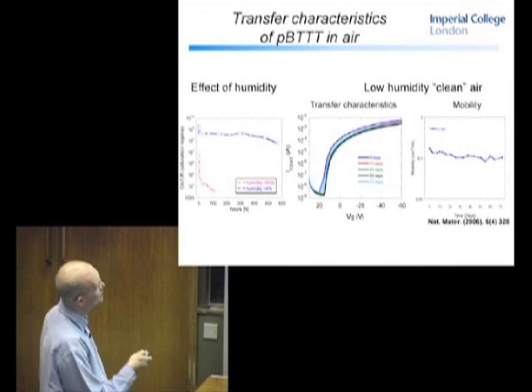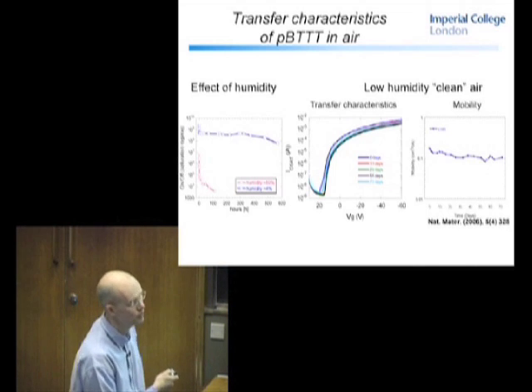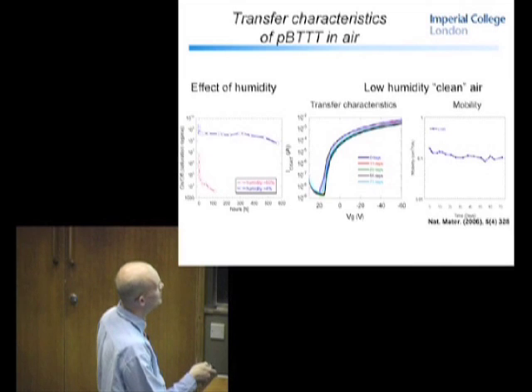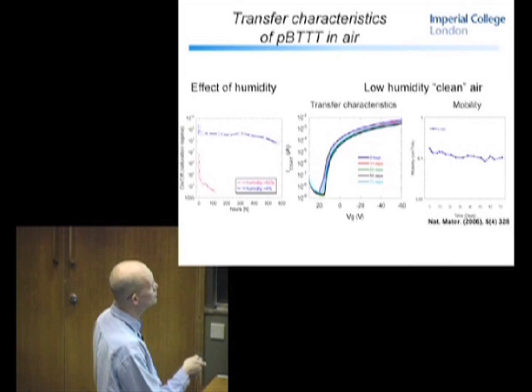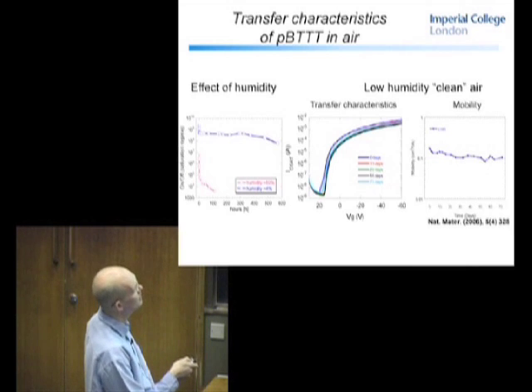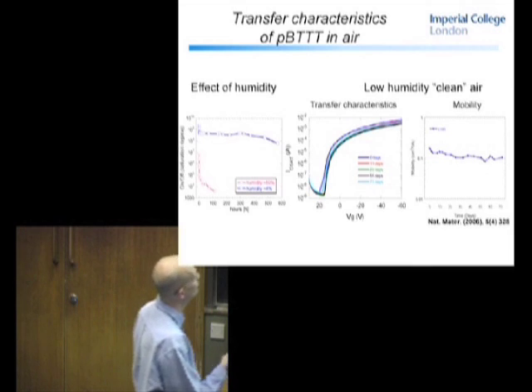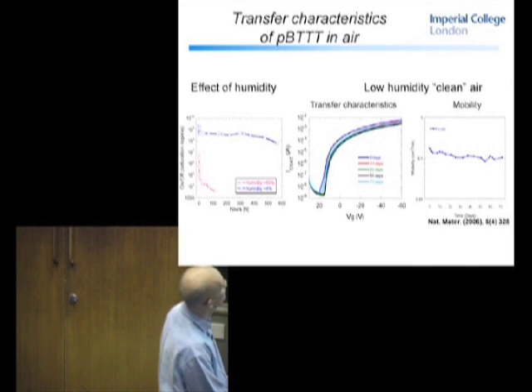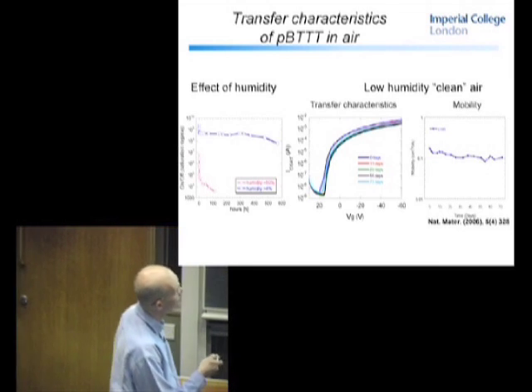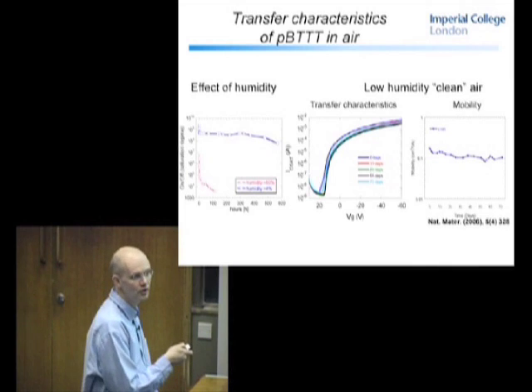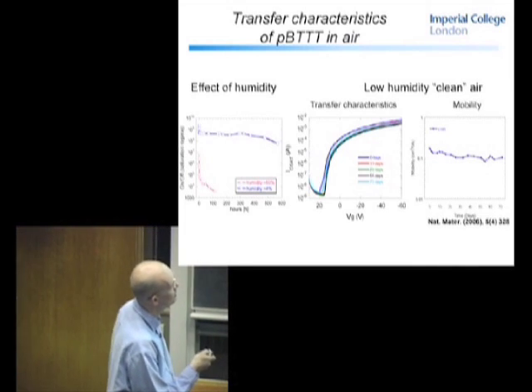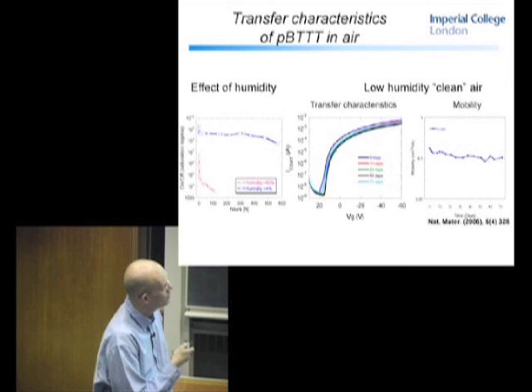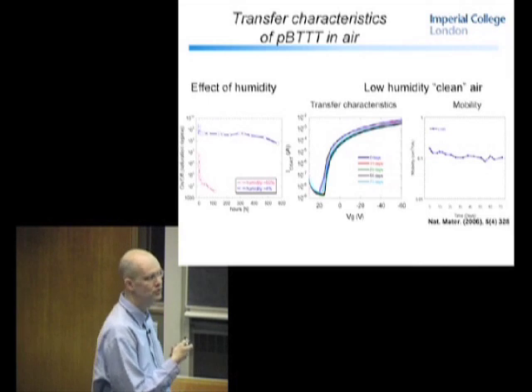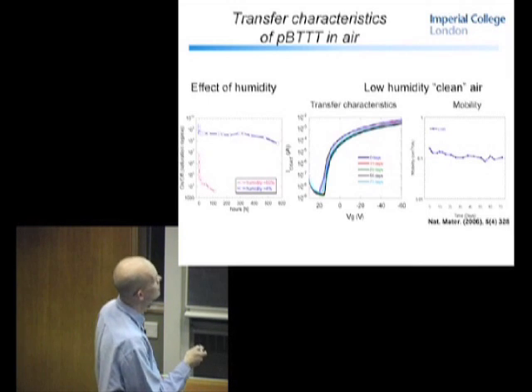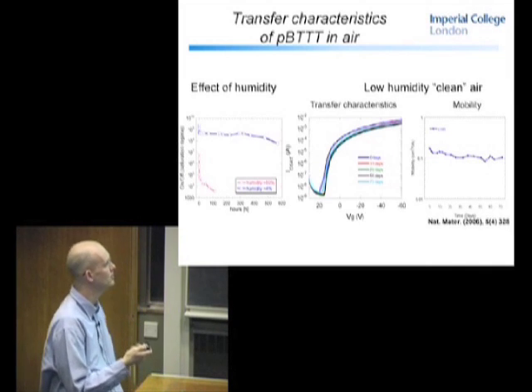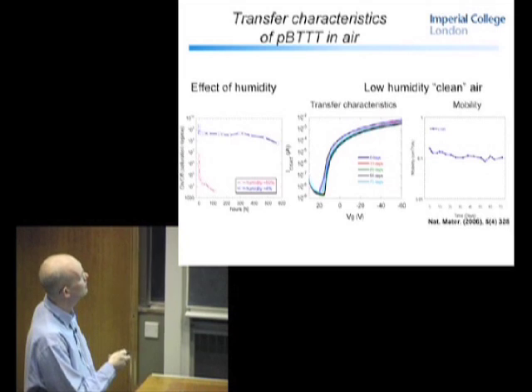But interestingly, when you clean up this air, originally we thought what we were doing was just removing the water from this whole redox equation, and here for 72 days you see pretty reproducible transfer characteristics. So in a low humidity clean environment we get nice transistor performance. I thought I had another slide on this. But I have this 'clean' in inverted commas, and what we're starting to think is that in fact this is due to the sort of pollutants in the atmosphere. It's more due to ozone and nitroxides than it is to moisture. So in fact you could operate devices in ambient conditions if you remove ozone and nitroxides.